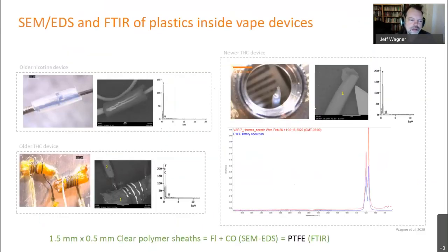Here's another type of polymer-based item that wasn't in the previous cartridge, but was in several others. It's this clear sort of plastic sheath, about 0.5 millimeter by 1.5 millimeters. We found high concentrations of fluorine by SEM EDS in this polymer, which led us to believe it is a fluorinated polymer, but with FTIR, we were able to confirm that it was PTFE.